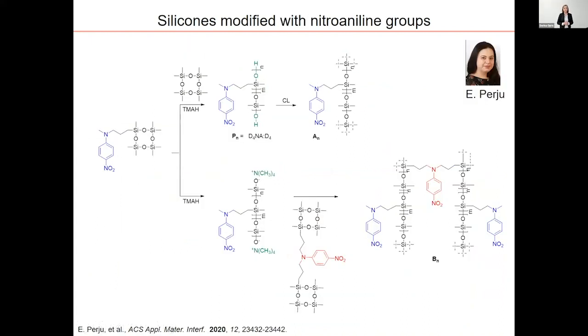To achieve such materials, we started with this polar monomer, and what we did is either to polymerize or to copolymerize with this nonpolar monomer over here. So first we prepared the polymers and copolymers. They have hydroxy groups, which we use subsequently for cross-linking into thin films. I will refer to these materials as material A.